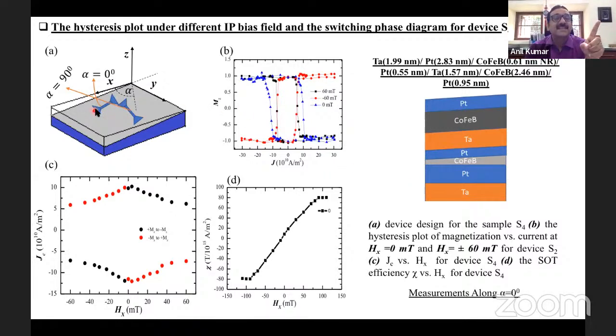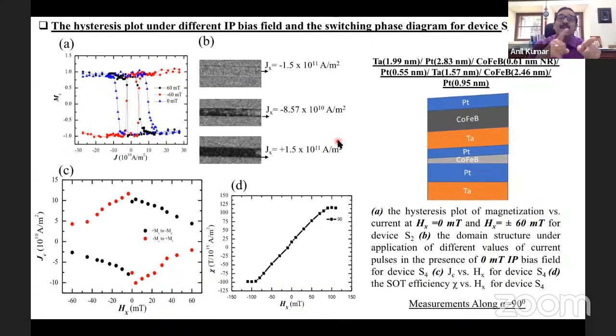In this kind of scenario, even when I apply the current along the thickness gradient direction, even at zero applied magnetic field, I'm able to switch the magnetization. So now just by adding a ferromagnetic layer, that is substituting the requirement of applying an in-plane magnetic field. Now, along the other direction, it is always there.